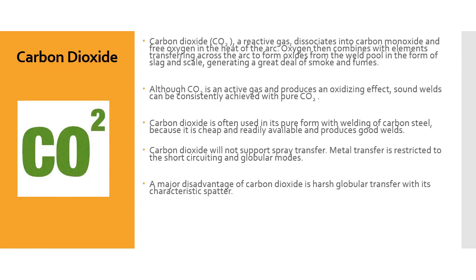Carbon dioxide is a reactive gas. It disassociates into carbon monoxide and free oxygen in the heat of the arc. Oxygen then combines with elements transferring across the arc to form oxides from the weld pool in the form of slag and scale, generating a great deal of smoke and fumes. Although CO2 is an active gas and produces an oxidizing effect, sound welds can be consistently achieved with pure carbon dioxide. Carbon dioxide will not support spray transfer — there is no road leading to spray transfer with carbon dioxide.